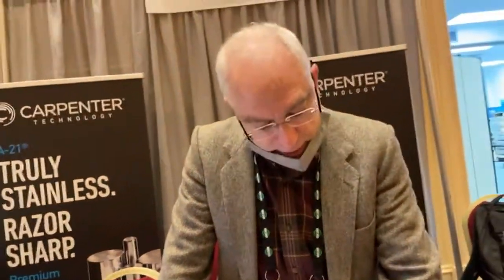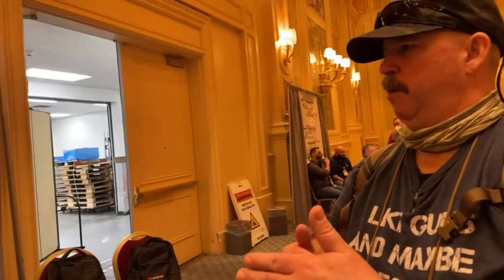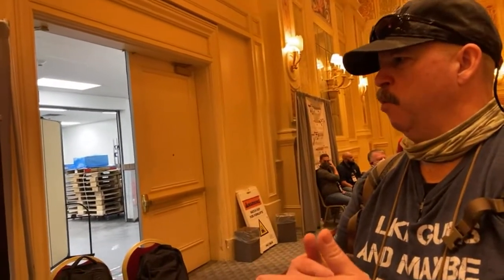So this is earth shattering, because no other metal on earth that I know of can give you 62 and look like that after 200 hours in that salt fog environment. So it's truly just being able to get it up to 62. You know, the percentage jump in wear value going from, say, 58, 59, 60 to 62, that's a huge jump. Yes, it is. It's a huge jump in wear potential.